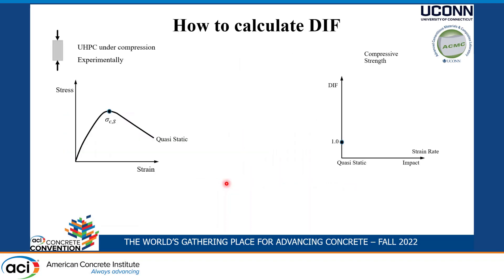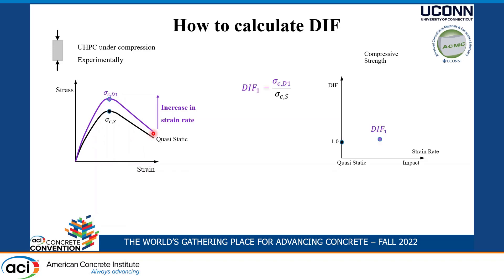Let's talk about background: how to calculate a dynamic impact factor. Take a compressive cylinder, load it top and bottom experimentally, and you get the stress-strain relationship under classic static loads — maybe taking a minute or so. Then you increase the loading speed, increase the strain rate, and your material's response changes. You can take the strength value at that point and divide by the static value to get a dynamic impact factor larger than one, plotted against strain rate.